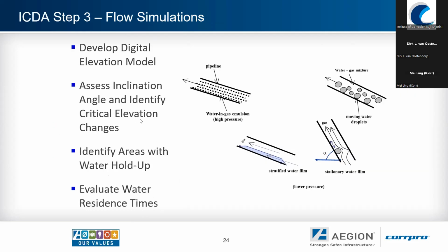So then we turn into the flow simulations. This is, again, quite a process. We start to develop the digital elevation model, electronic wire line of the route of the pipeline, the topography of the pipeline and profile in 3 dimensions. So wherever there's changes or bends or whatever, that's all taken into consideration. We do the inclination angle, the critical angle assessment to sort of determine if there's any specific areas where water holdup may become more of a problem. And then one of the key things is to evaluate the water residence time. I'll talk about that and show examples of that.